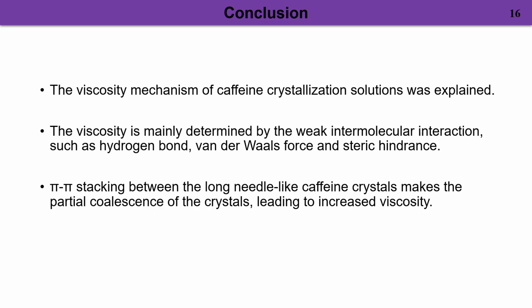Simultaneously, there is pi-pi stacking between the long needle-like caffeine crystals, which makes the partial coalescence of the crystals, leading to increased viscosity. And in conclusion, this work has demonstrated that the weak intermolecular interactions cause viscosity in the crystallization solution.